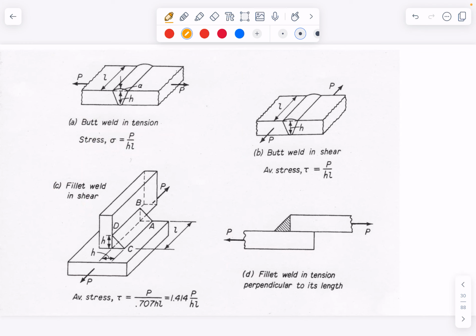Okay, so if we look at a butt weld in tension, the stress created from this load P is P over H L. Now I'm using H over L here because this is what conventional theory says. Right? This probably over-exaggerates the stress in the weld, but that's far better than underestimating it and having it fail.